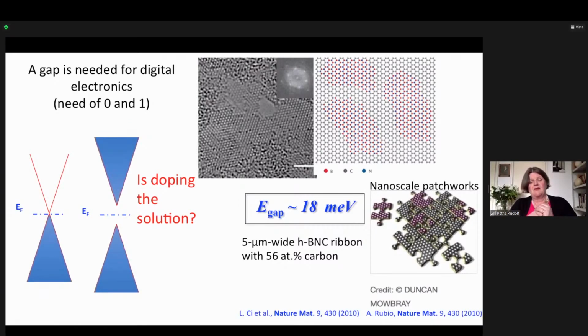From semiconductors, we know that doping can be used, and also here doping can be used even if it is a semi-metal, because the density of states at the Fermi level is very small. So what one can do is to dope it with boron and nitrogen, and then a gap actually opens. But the problem is that you actually phase separate. The boron and the nitrogen don't like to mix with the graphene, but you get islands of boron and nitrogen in the middle of the graphene.